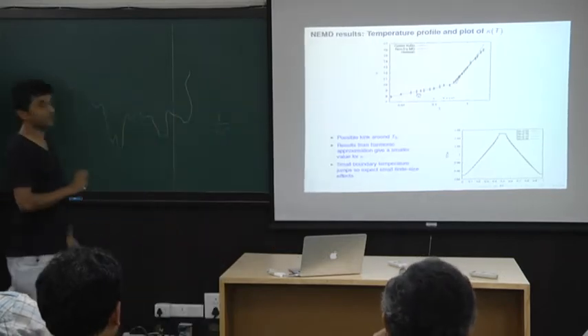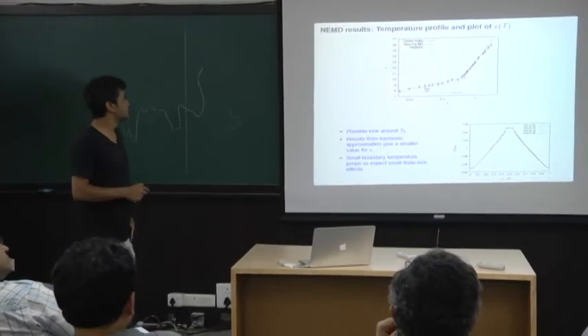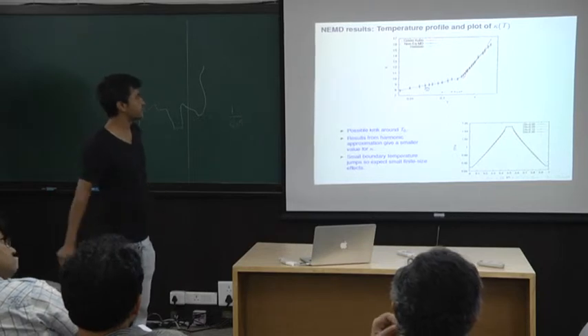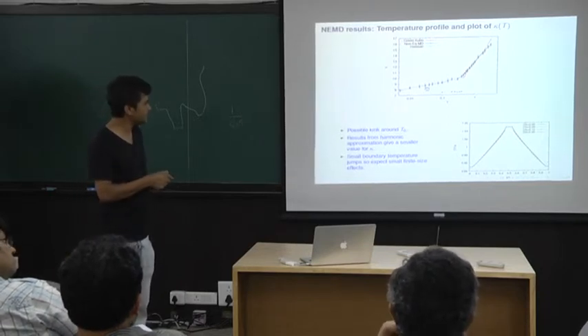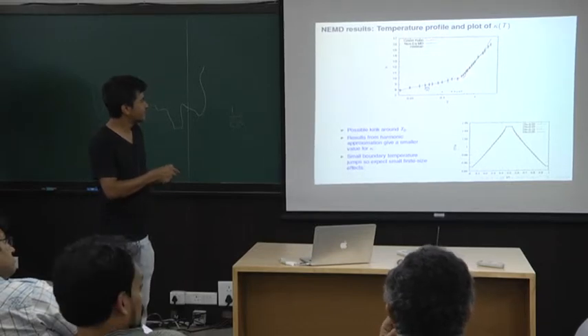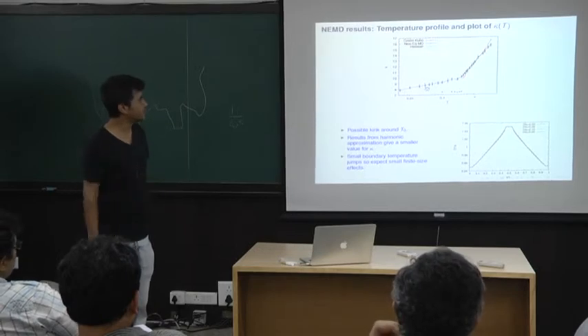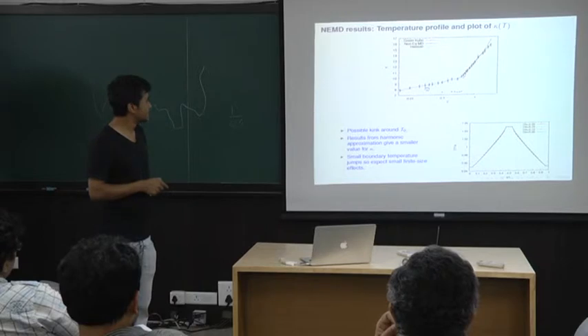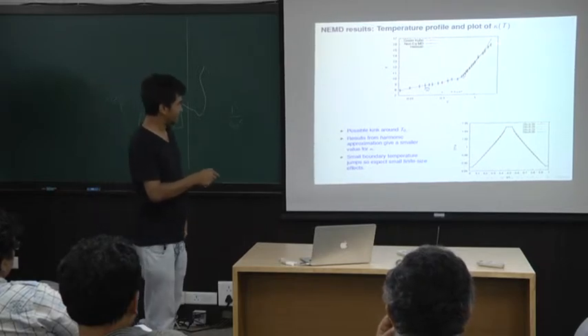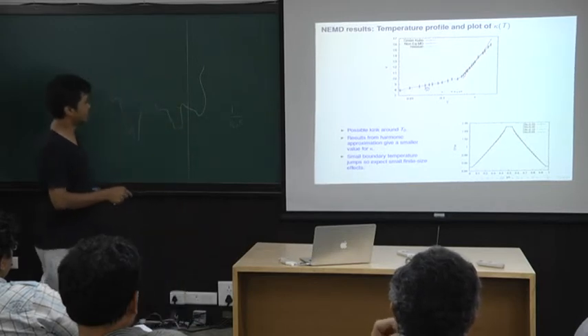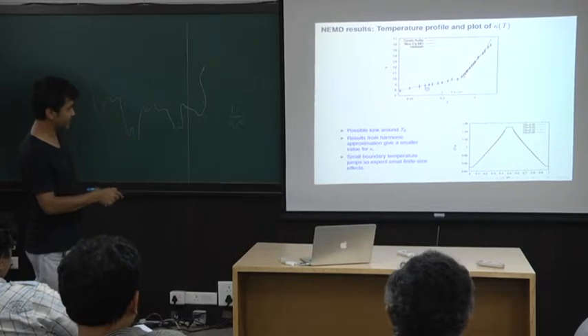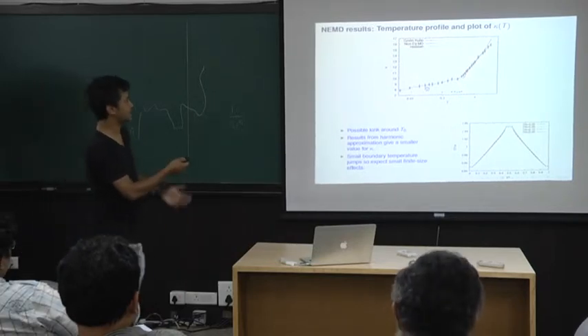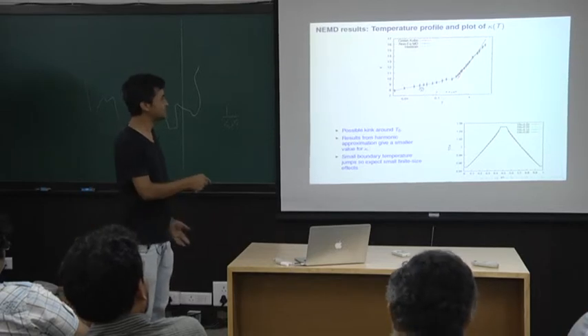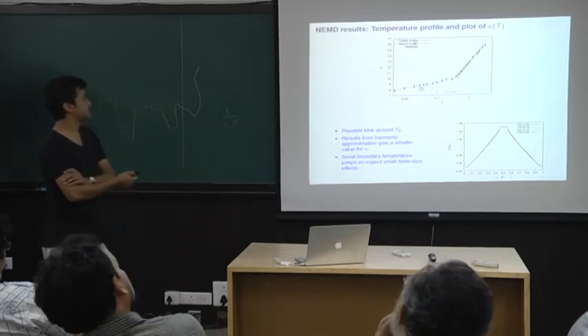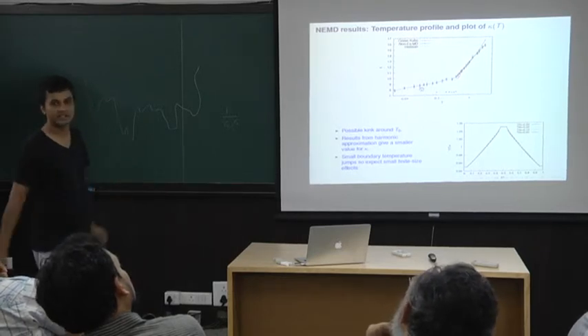Okay, so here are the results from the NEMD, non-equilibrium molecular dynamics simulations. Here I am plotting the conductivity as a function of temperature. The blue line and the black data points are from the NEMD simulation. The red line is from Green-Kubo equilibrium simulations, which still have not been done out here. They are of course matching quite well, and the T naught is somewhere around here, and maybe there is something. It's not very clear now, but maybe something is happening, right? There's a sort of kink. This is something we need to really examine more carefully. But right now it looks at least like there's something happening at this temperature.